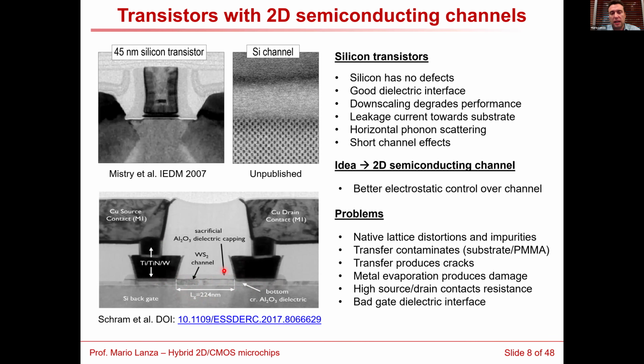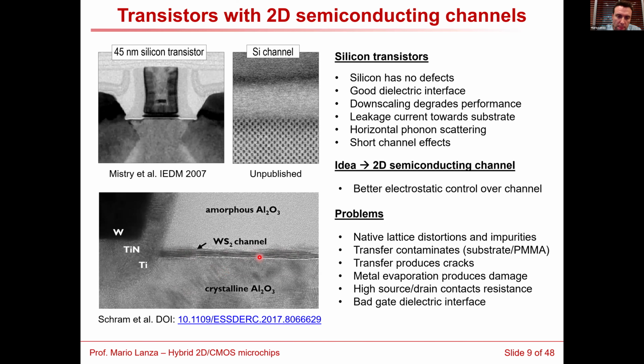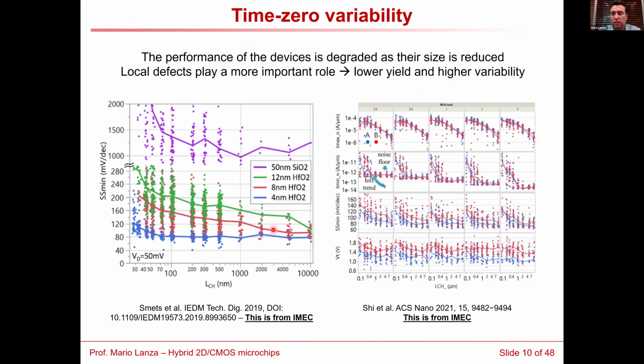in fact, these materials can have some impurities and some defects, like lattice distortions. Also, if you need to do the transfer, you're probably going to have contaminants from the substrate and from the PMMA that you used for the transfer. Also, the transfer may produce cracks, which may reduce yield. The metal evaporation can also produce some damage to the 2D material. Basically, we have observed a high source-drain contact resistance and a bad interface with the gate dielectric. Nevertheless, several people have managed to fabricate relatively large transistors using this approach, with gate lengths normally higher than 1 micrometer, and they show some reproducibility.